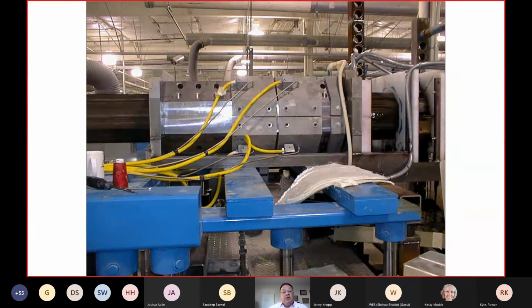So we are much stronger. Remember, we engineer steel around 25,000 psi, and we do 4 to 5 times that for aluminum. But when you look at strength divided by density, that's when you see the real big benefit, because steel is about 7.84 for specific gravity, aluminum's 2.5, and an FRP laminate is about 1.85. So when you look at strength per unit weight is where you see the real big benefit.